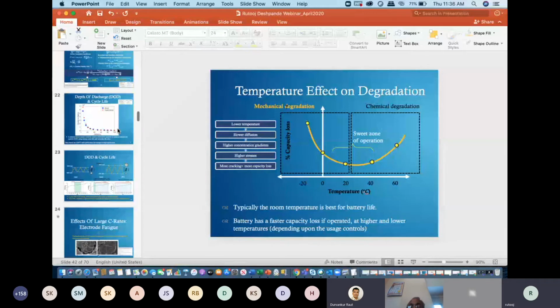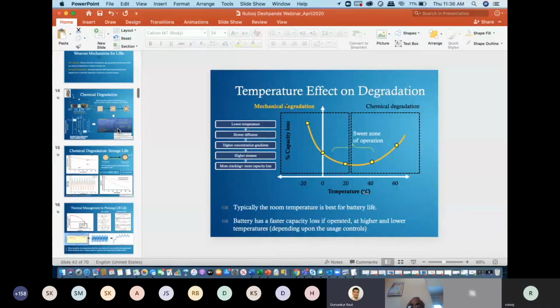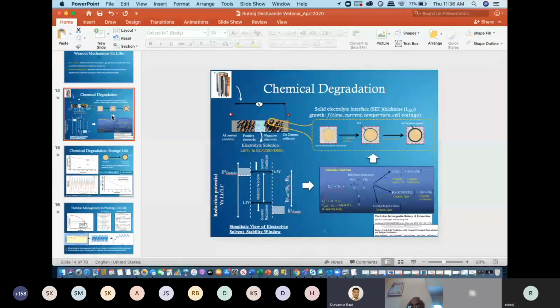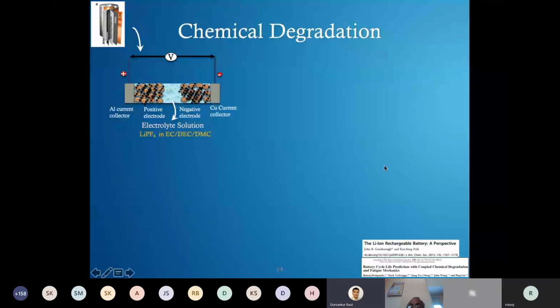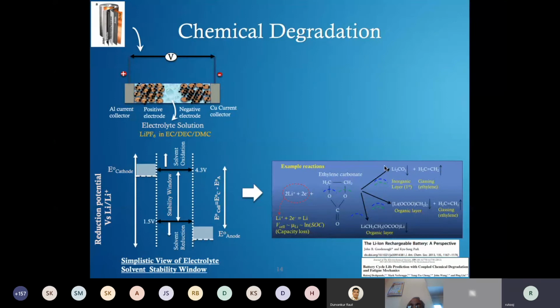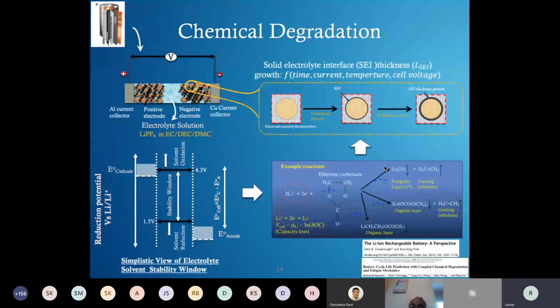Yes, yes. So the next question is about SEI layer thickness. What is the typical SEI layer thickness, and how long will it take to achieve 1 millimeter of thickness? So I guess the thickness is in nanometers, right? It is very, very small. It would be around a few nanometers to start with and grow to say a maximum of 1 micron, 2 microns, or a few tens of microns at max. It won't go to millimeters at all. So the cell expansion is not happening because of SEI. If the question here is that cell expansion would be different due to SEI thickness, that's not true.